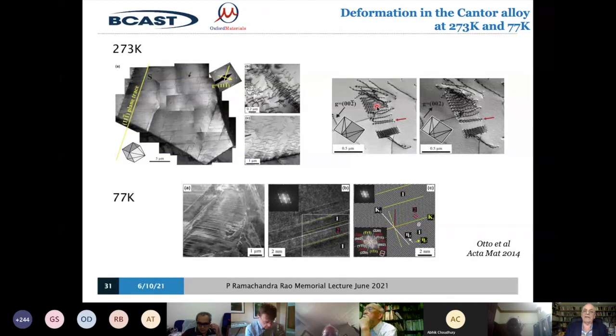Now this picture is exactly what you would find if you looked at the deformation of pure single crystal copper or pure single crystal gold. It looks exactly the same. It's planar slip, to use the technical language. And at some point you begin to get a bit of cross slip, but those are the technical details. It doesn't really matter. It's very similar. So how come the strengths are so high in this single phase FCC material?